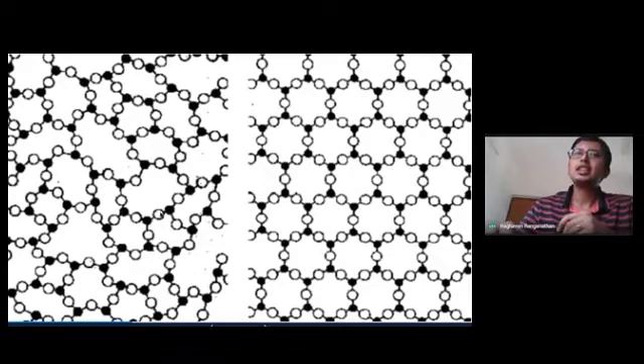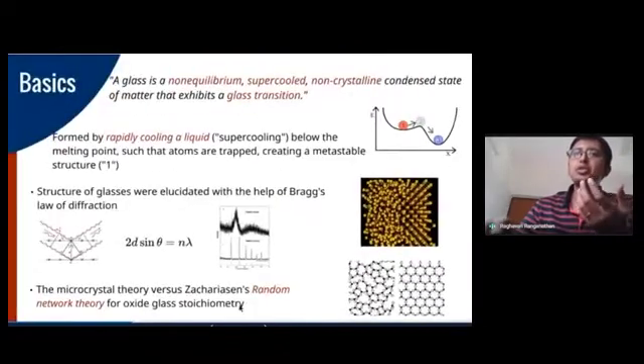But what you see on the left is again a silica network. This network is formed from the silicon atom and the oxygen atom linking with all its neighboring silica tetrahedra. So each unit that you see here is a tetrahedron, and all these tetrahedra link up together to form a strong rigid network. So silica can exist both as a network in a crystalline state on the right and a completely glassy state on the left. This led Zachariasen to propose his now very famous random network theory, which later turned out to be very true in predicting the structure.